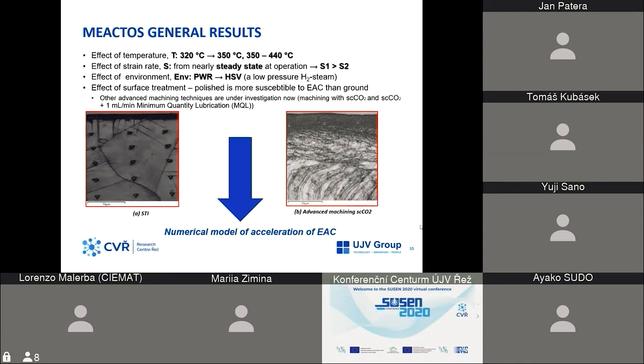We saw that the polished surface is more susceptible to EAC than the ground, and in the MEACTOS project we use more advanced machining techniques which we investigate. It's a machining with supercritical CO2, with lubrication or without lubrication. So here I just put some examples of the surfaces. It's a standard industrial technique of the surface of the sample. You can see an ultrafine grained layer under the surface of the sample, and this is an advanced machining, supercritical CO2.